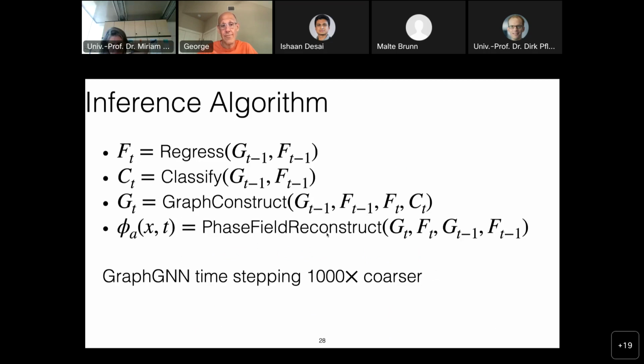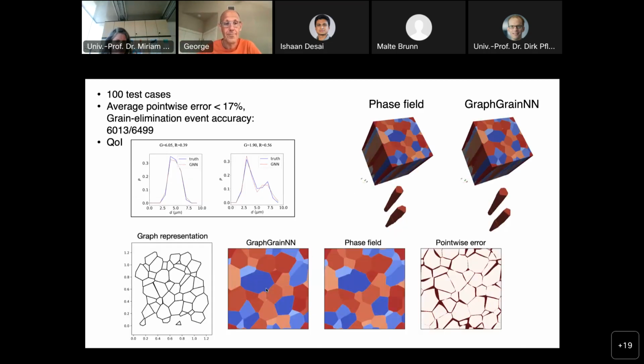And then once we have the graph, we can reconstruct the phase field using the graphs at two time snapshots. And the main idea is that the time stepping is 1,000 times coarser than the actual PDE. So I'm running out of time, but I just want to show you some representative results. The training is about 1,500 3D phase field simulations. Again, the same idea: we train with a small number of grains, and we're going to extend it to an arbitrary number of grains. So we train with about 20 to 50 grains, because it's a random variable.